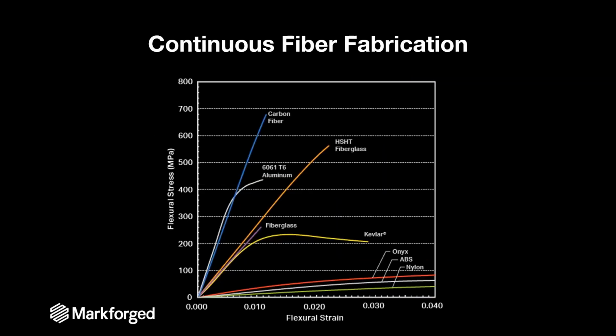Stress strain curve. The main takeaway from this guy is if you look at the white 6061 aluminum, you have an inflection point and it's right around where the carbon fiber interacts, or intersects, I should say, 6061 aluminum. And so when we say as strong or stronger, this is the data. This is the data that we're referring to.